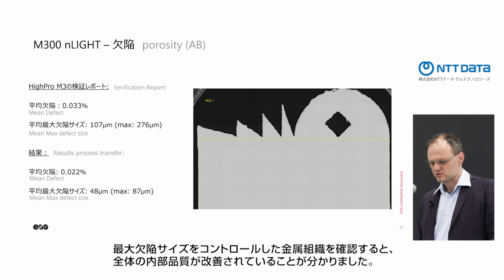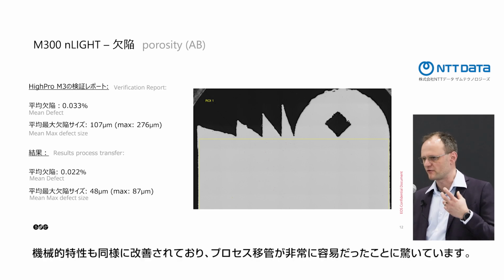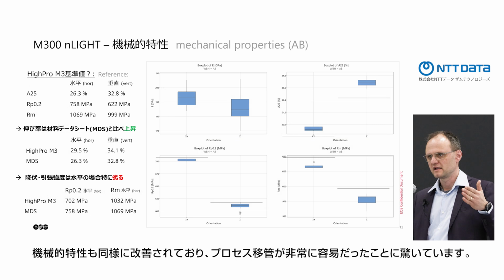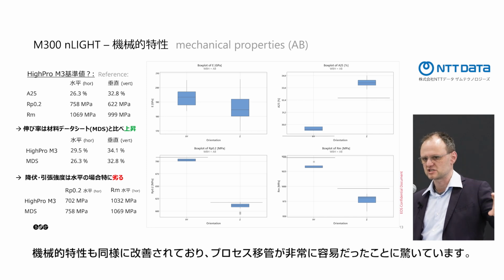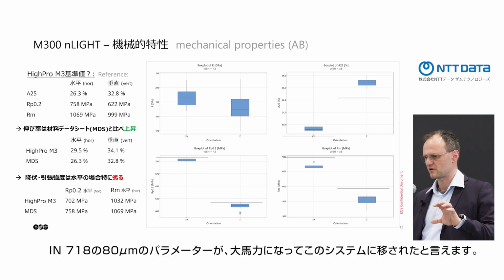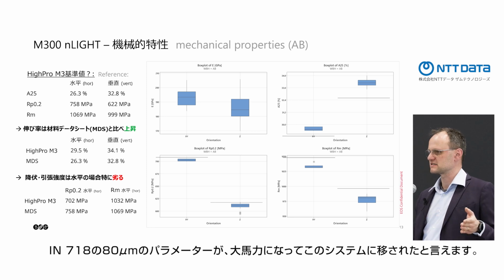We've checked that the microstructure and the maximum defect size are controlled, and the process results actually show us that on that system it's even getting better. So we were very positively surprised by how easy the transition is. Same with the mechanical properties. They are at acceptable levels, but this is really just a process transfer: 80 micron 718 Inconel parameters transferred to this system with a lot of horsepower.